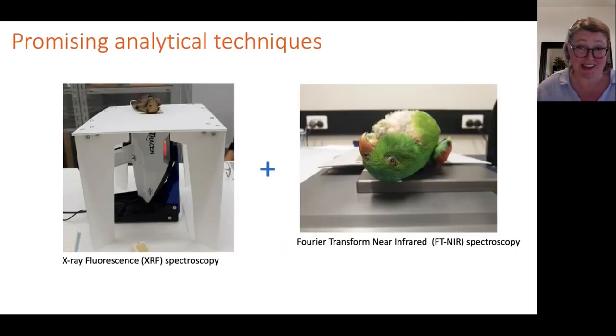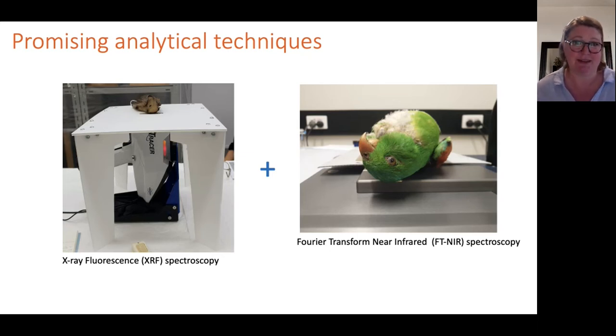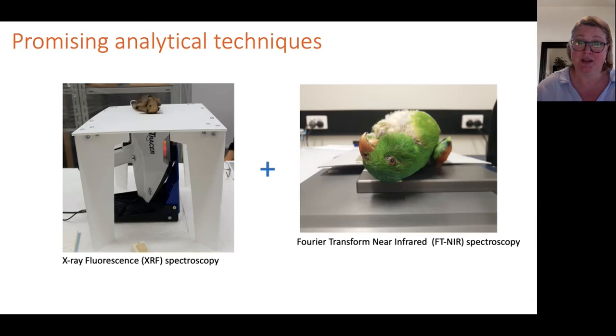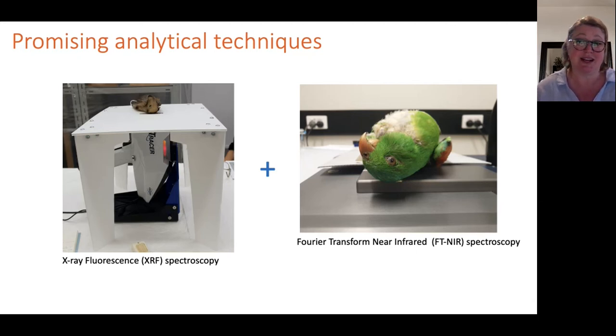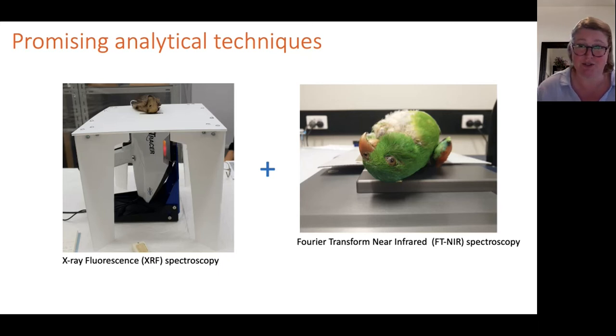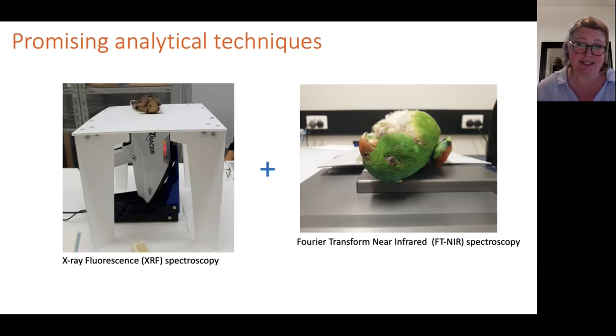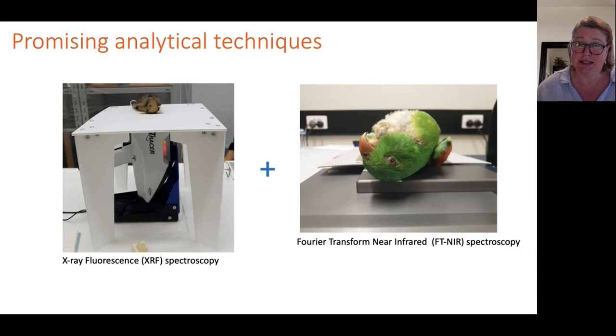I found two promising techniques: portable X-ray fluorescence spectroscopy and Fourier transform near-infrared spectroscopy. With some additional support, both techniques allow the specimen to rest under its own weight while being analysed, rather than being physically sampled or compressed. Low-intensity X-rays pose little risk of damage to DNA, and low-intensity, low-wavelength infrared light has been shown in medical research to have very minimal impact on biological materials.